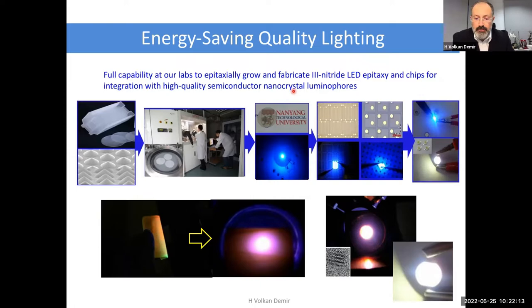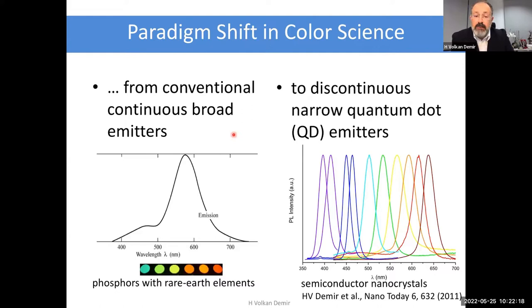This therefore has been indeed a paradigm shift almost one decade ago, because previously it was believed that using conventional continuous broad emitters, one can achieve better white light. And our hypothesis was, on the contrary, using discrete emitters, which would be formed of a number of sharp emitters, such as colloidal quantum dots. You see some examples of that. With the right strategy combination, we can do better. And this is now quite well recognized, particularly for the red region. And in the commercial world now, you can actually find the best LEDs using nanocrystals to have this type of discrete emitters.